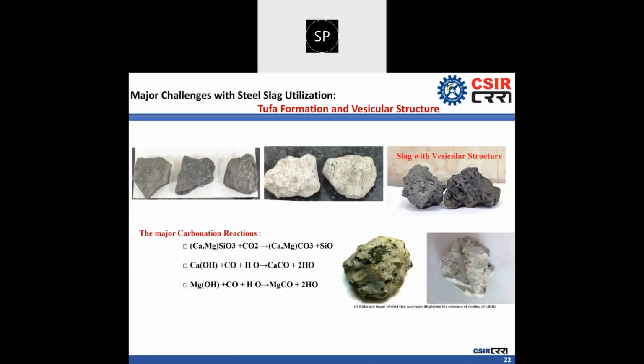Now, the second major challenge is tufa formation. The slag aggregate, due to the presence of high calcium oxide, can ooze CaCO3, a calcium carbonate deposit, which is deposited on top of the steel slag road layer. This sort of thing can impede the water drainage characteristic. Therefore, before its application, it should be treated.